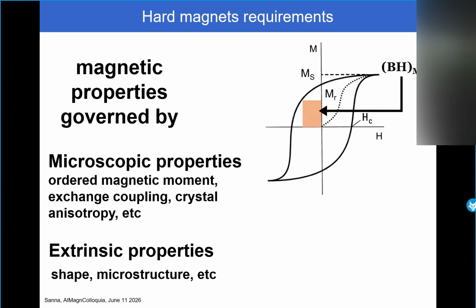And this is some very general overview regarding what we are doing. Typically, to have hard magnets, we need to improve their properties. What does it mean? It means that for sure we need to increase the coercive field, because we need a large hysteresis loop. And in general, the magnetic properties of ferromagnets are governed by both microscopic properties such as ordered magnetic moment, exchange coupling, crystal anisotropy, which are material dependent, and extrinsic properties such as the shape, the microstructure, etc., which depend on how we are able to engineer these materials.